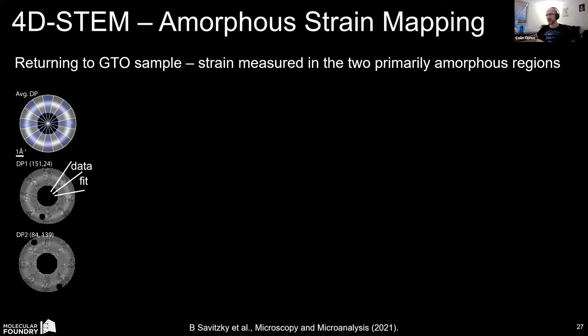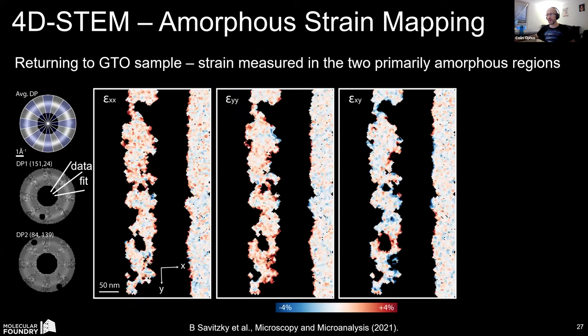And so going back to the gadolinium titanate, if you remember, we had that mixed amorphous polycrystalline region in the middle of the field of view and, on the right-hand side, the fully amorphous region. And this is showing those strain tensor measurements of those two zones. And you can immediately tell them apart.